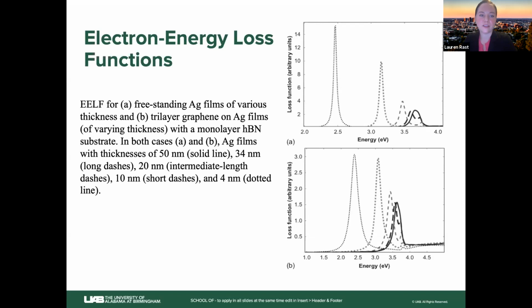So here we have electron energy loss functions for silver, just to compare silver films of various thicknesses, going from 50 nanometers down to 4, where we have the dotted line. And then in B, 3 layers of graphene on silver with a monolayer hexagonal boron nitride substrate. It turns out that the spectral profile we see with hexagonal boron nitride is really similar to what we would find in the literature for a suspended sample of graphene. There's no substrate there, except that it helps the graphene sample stay flat and preserve the electron transport properties of graphene.